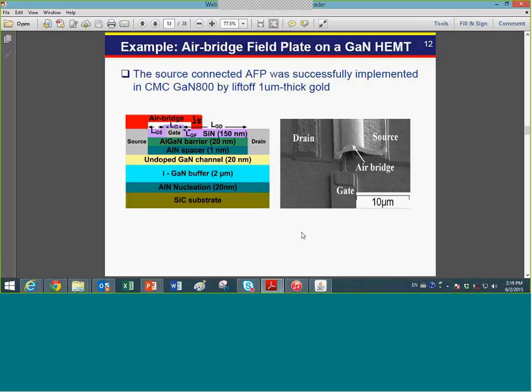And here is an example that was done by the CMC, CFP, what is it? I forgot. So this is a technology available through the CMC gallium nitride process, now moving down to maybe 0.5 micron. The final layer of gold metal was done by liftoff. This is a device we developed through this technology. So you see, we built up the air bridge of gold nicely to avoid field crowding and improve this device. It's an gallium nitride HEMT device with a breakdown voltage over 500 volts.